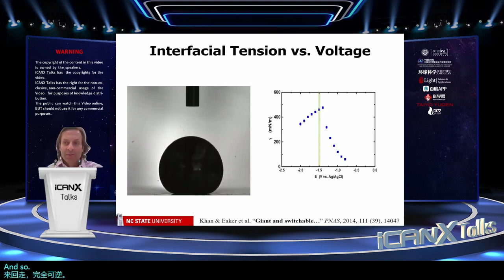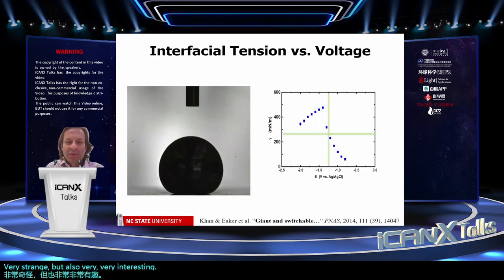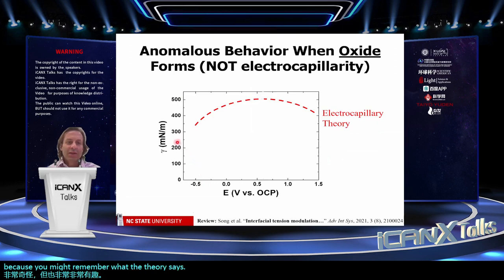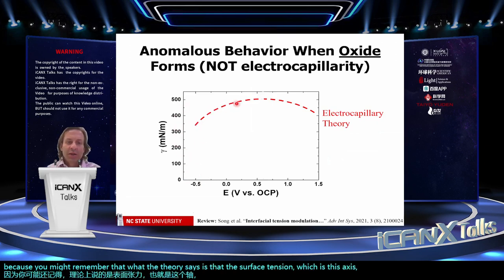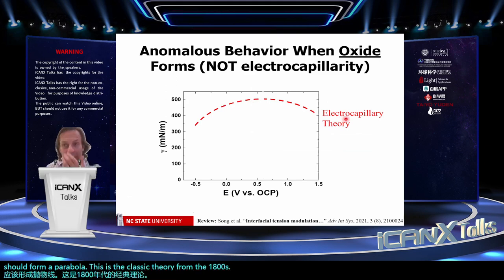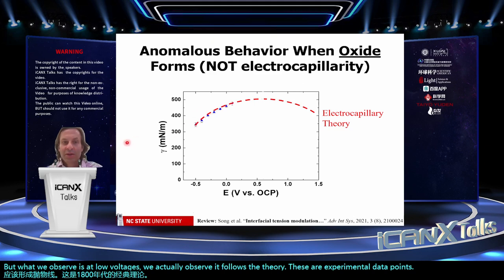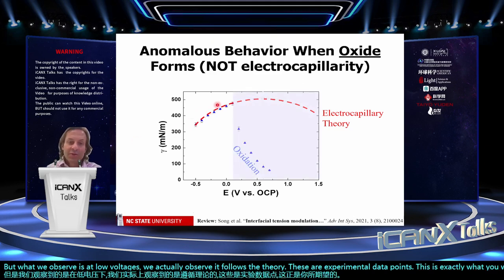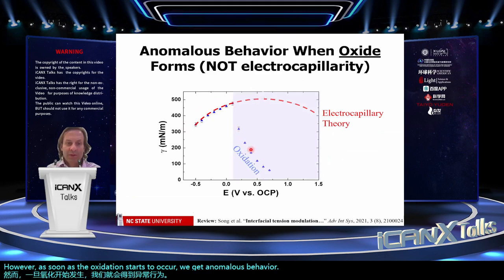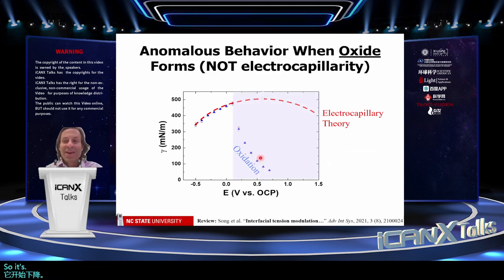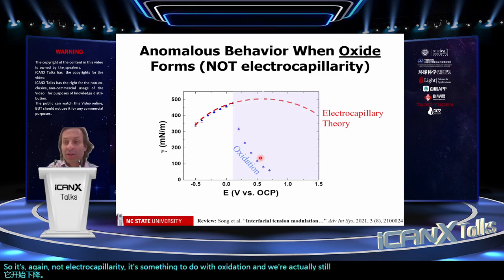And so this is very strange, but also very, very interesting, because you might remember that what the theory says is that the surface tension, which is this axis, should form a parabola. This is the classic theory from the 1800s. But what we observe is at low voltages, it follows the theory. These are experimental data points. This is exactly what you would expect. However, as soon as the oxidation starts to occur, we get anomalous behavior. It starts to drop. So it's, again, not electrocapillarity. It's something to do with oxidation. And we're actually still trying to understand this at a deeper level.